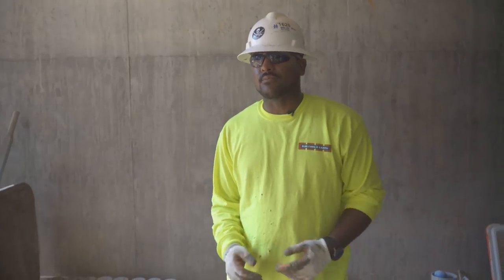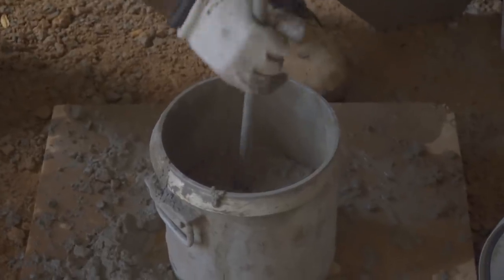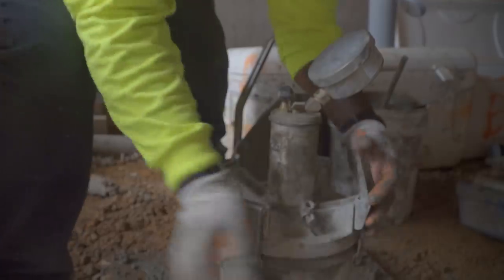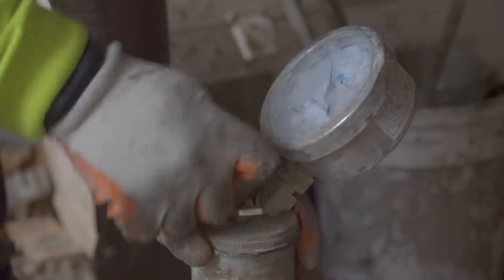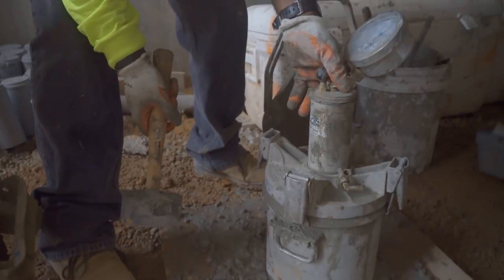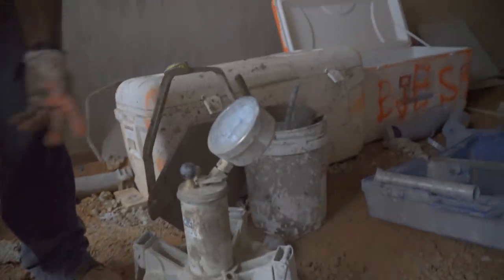What we have here is our air test. We do it after the slump to measure the trapped air inside the concrete. This mix is supposed to be four to six percent. We do it the same way as the slump — the only difference is we tap each layer 12 to 15 times after rodding it 25 times. Then we put our lid on top, add air, shoot through to get all the air bubbles out of the concrete, and pump it up to our initial pressure. We close the pet cocks and read the result — this one is 5.5, so it's within spec.